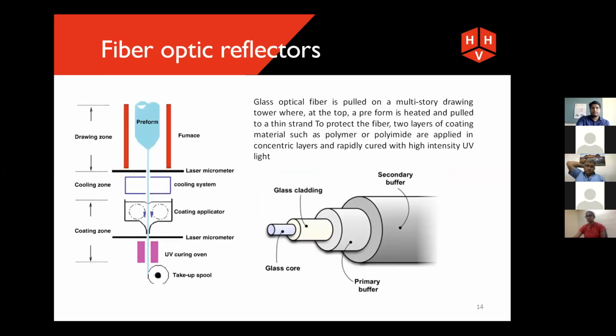The other applications are in the fiber optic industry, where UV comes in the form of fiber optic reflectors. The glass optical fiber is pulled at a multi-story drawing tower where a glass preform is heated and then pulled into a thin optical fiber. To protect the optical fiber, two layers of polymer material are applied, and then the UV curing system utilizes the UV reflectors to rapidly and evenly cure the fiber optic cables to form core-to-clad bonding, using high intensity UV light. The UV cured optical fiber coating closes the notches and prevents cracks, and it protects and strengthens the optical fibers.